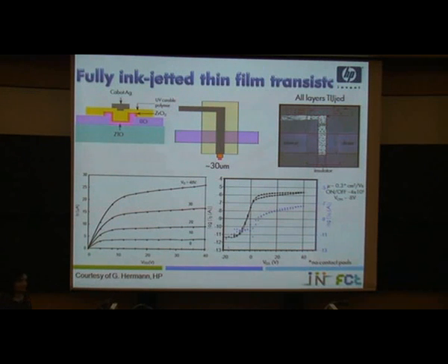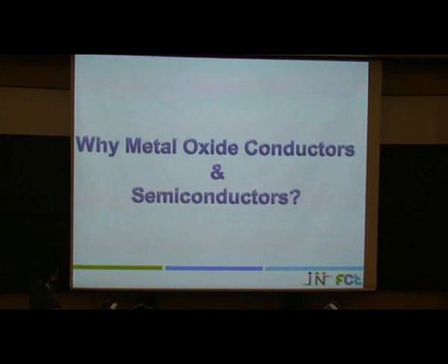And since we are not using lithography, this is an additive process, the cost is quite low. Of course, the results are not so good, but they presented these 5 years ago, so I believe now they have improved a lot. But the first results are 0.3 square centimeter per volt per second for the mobility, the on-off ratio not too high, 10 to the 5, and the V-on quite high in absolute value, 8 volts. They work in depletion mode.